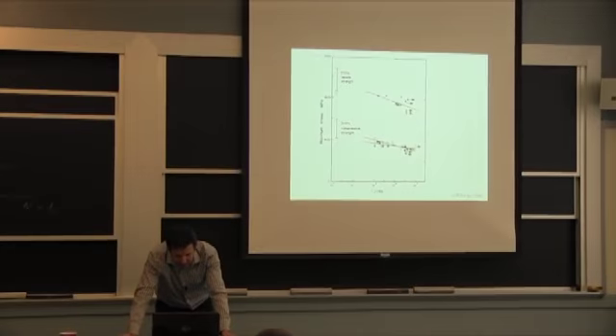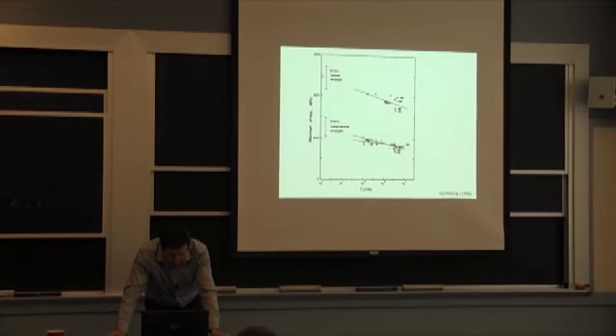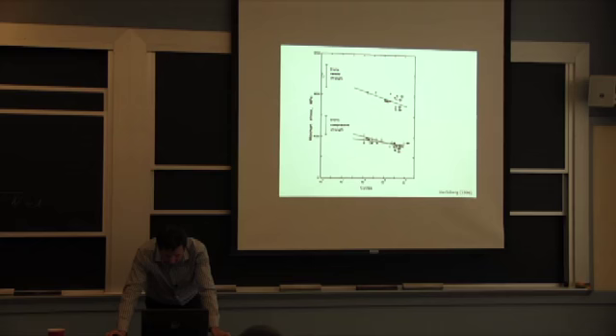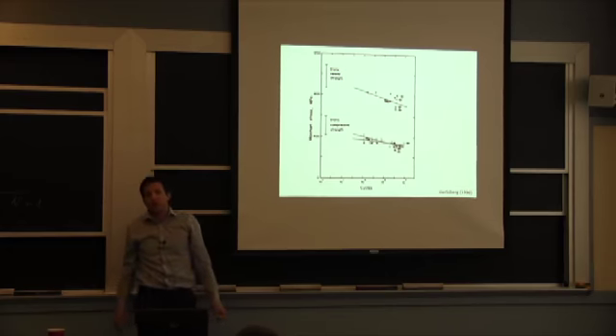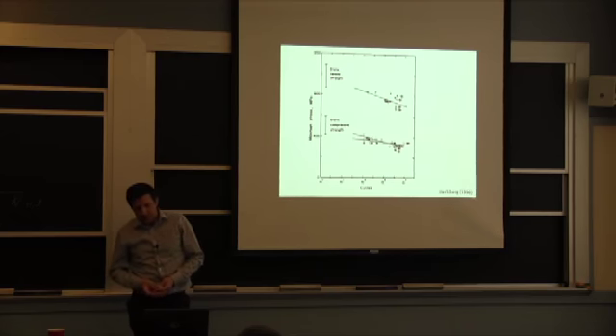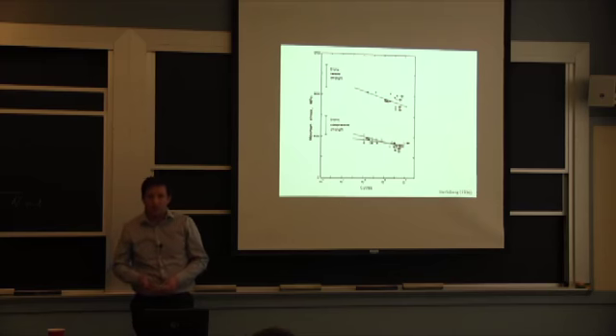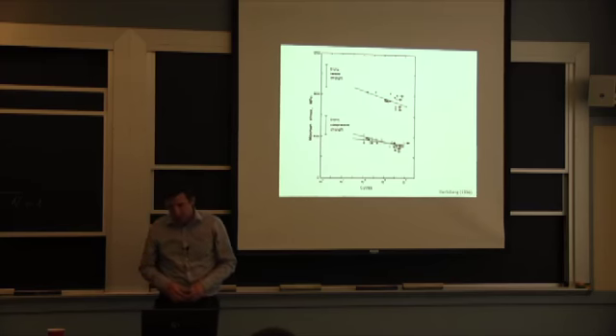So what I should do here is just a ratio presentation, and that's what this is showing. You have a static tensile strength of, say, about 900 megapascal, and if you go to 10 to the 7 cycles, you're still above, or around, 700. So it's a higher ratio of the fatigue limit over the tensile strength, and it's not unusual across the board with composites when your reinforcement is effective in bridging cracks.